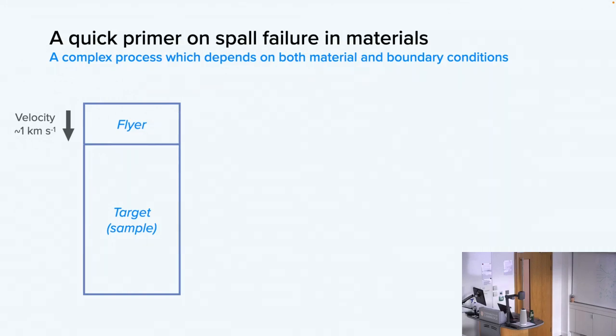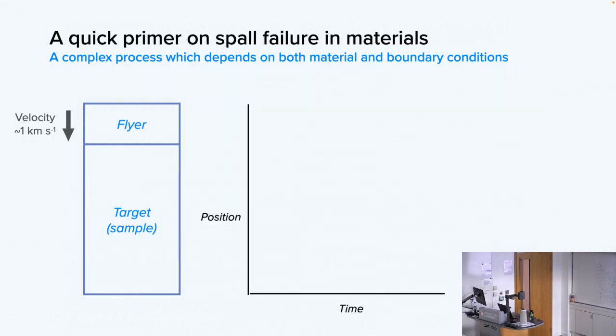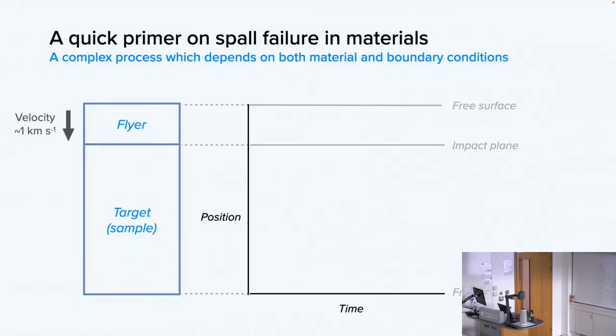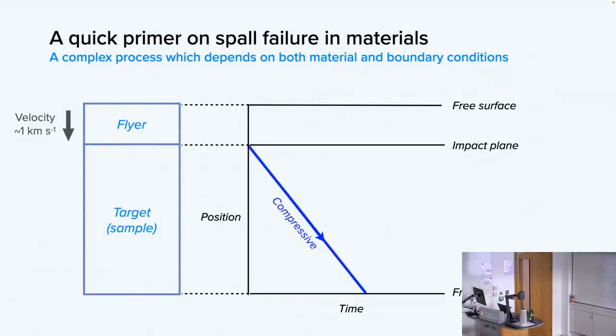And now what we want to do is track how the different waves in the target and the flyer evolve over time. So we're going to create a diagram that looks like this. On the vertical axis is position, and this maps directly onto position on the diagram at the left. Horizontal axis is time as waves propagate. And we're going to keep track of 3 important surfaces. So there's the impact plane between the flyer and the target. That's where our shock wave is going to initiate. Then we're going to have the back surface of the target, which is a free surface. And then we also have the back surface of the flyer, which is also a free surface.